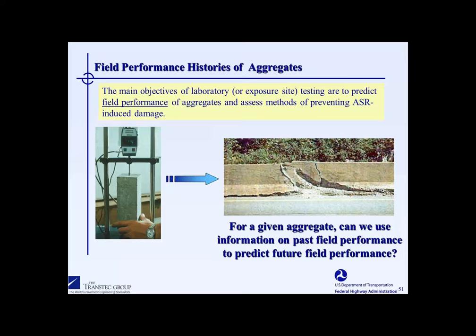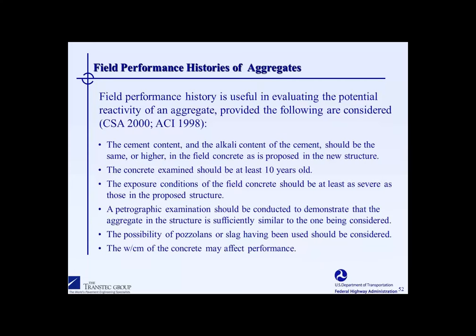With regard to field performance, one question that's often asked is, for a given aggregate, can we use past field performance to predict future field performance? And the answer is yes, maybe. If all of the criteria in this slide can be met, then you'd have a reasonable ability to predict future performance. You would have to make sure that the concrete that you're considering to be cast is essentially identical to concrete that's been out in the field for a long period of time.